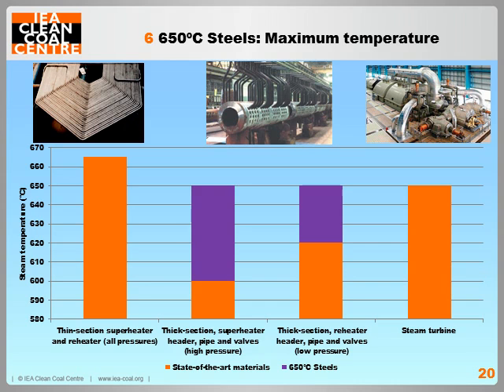The orange bars illustrate the highest steam temperatures achievable for commercial steels in major steam cycle components in modern ultra-supercritical plants. If steels can be developed for thick section components at 650 degrees Celsius, as shown by the purple bars, then ultra-supercritical power plants could operate at 650 superheat and 650 reheat temperatures, with a rise in net electrical efficiency of roughly 1 to 3% depending.